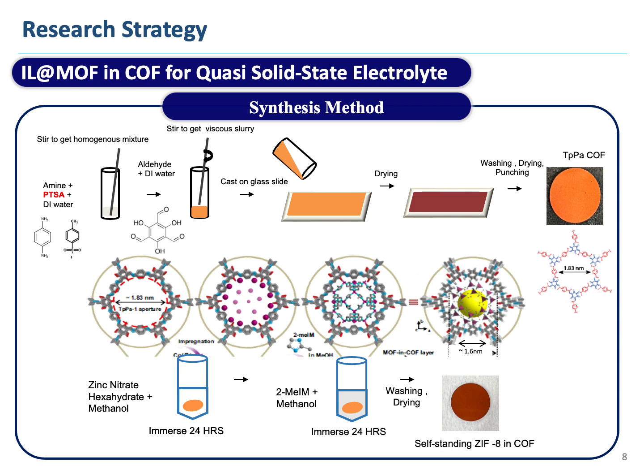The synthesis of IL and MOF in COF structure is as below. First, we mix amine and aldehyde with p-toluenesulfonic acid as the catalyst together to get a viscous slurry. Cast it on a glass slide, and after drying, washing, and punching, we'll get a TPPA COF film with a pore size of 1.83 nanometer. Then, by a two-step immersion process, we will get a self-standing ZIF-8 in COF, in which ZIF-8 has a unit cell size of 1.6 nanometer, which is able to be incorporated into TPPA COF. Then, this self-standing ZIF-8 in COF is doped with ionic liquid to form a quasi-solid-state electrolyte.